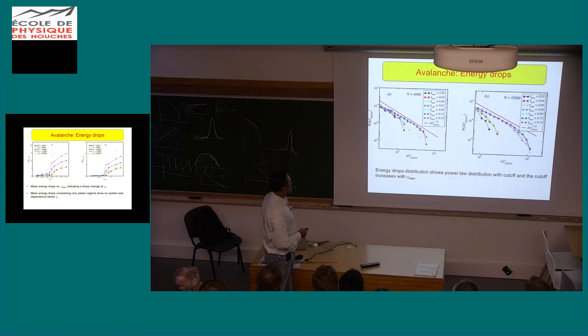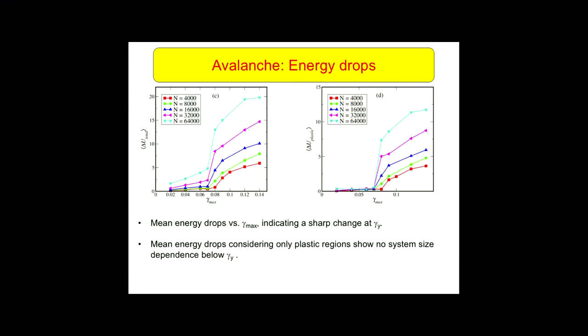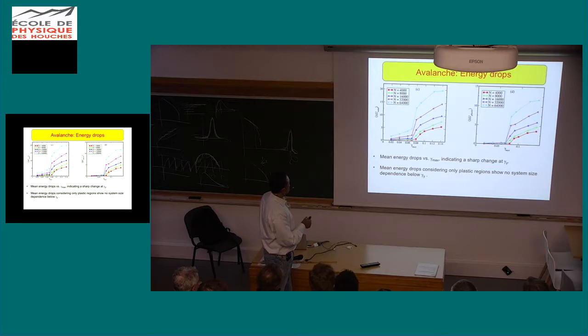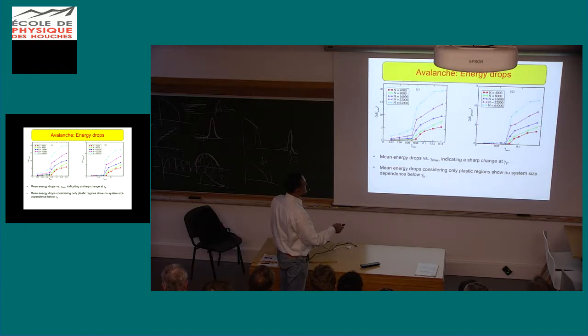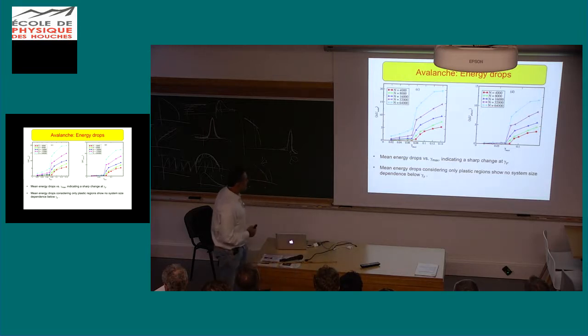So the energies do the same thing, but there's an interesting wrinkle. If I look at the energy drops as a function of strain amplitude for different system sizes, one sees in fact an independence both below the yielding amplitude and above. But if we follow a procedure of identifying what the energy change in the plastic core of the plastic event is, then we do see a behavior that's consistent with what I showed you earlier, where there is no significant system size dependence below, whereas there is above the yielding transition.